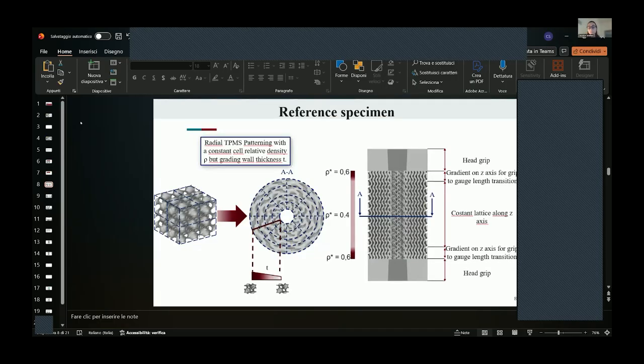Here I'm showing the reference specimen. It has a cylindrical shape, and we shift toward a radial patterning, imposing two different relative density gradients. The first one can be seen in the A section. Varying the wall thickness, we imposed a constant relative density equal to 0.4 in the constant lattice region, as you can see in the right part of the slides.